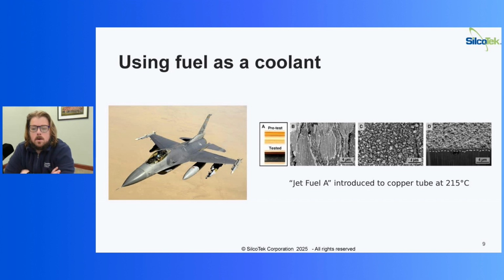And so here is just an image of a pre-test of a copper tube. So copper has really, really nice thermal properties. It's able to exchange heat very efficiently. However, it's very catalytic. So you can see as jet fuel A, which is what they were looking at, was introduced to a copper tube at 215 degrees C. You can see before the test, it's that nice coppery color there on the top. But underneath, after they flow this jet fuel A through at 215 degrees C, it becomes black.